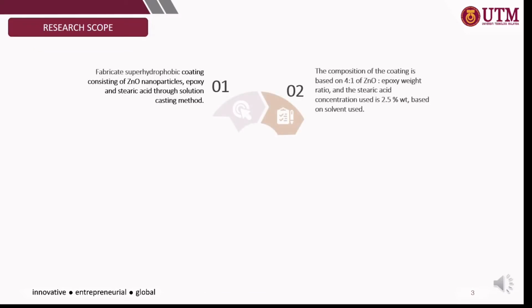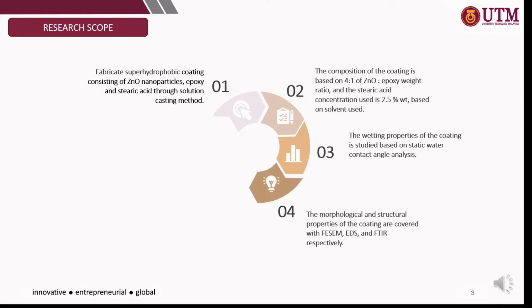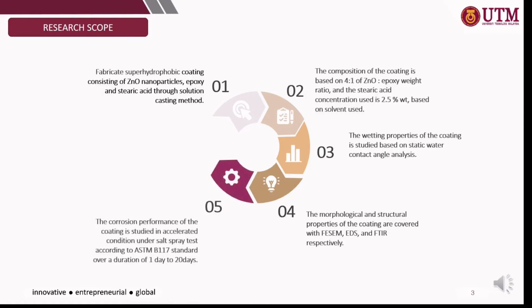The research scope of the study comprises the following parts. First, fabricate a superhydrophobic coating consisting of zinc oxide nanoparticles, epoxy, and stearic acid through the solution casting method. The composition of the coating is based on a 4:1 zinc oxide to epoxy weight ratio, and the stearic acid concentration is 2.5% weight based on solvent used. The wetting properties of the coating are studied based on static water contact angle analysis. The morphological and structural properties of the coating are covered with FESEM, EDS, and FTIR respectively.